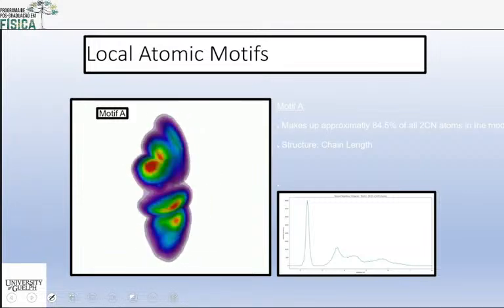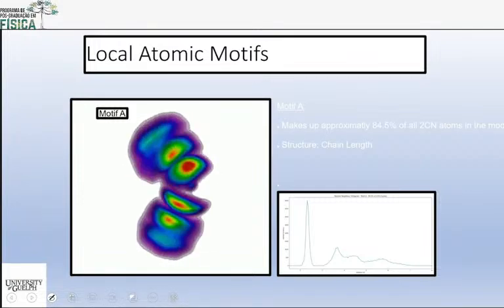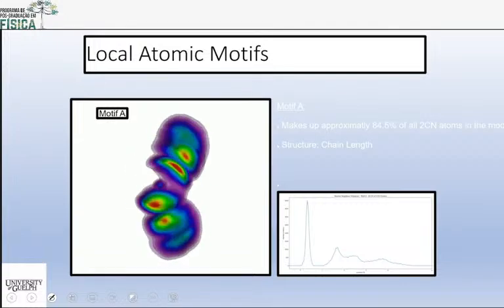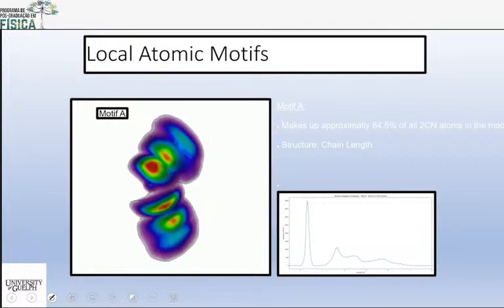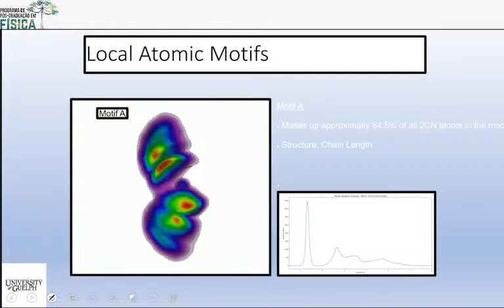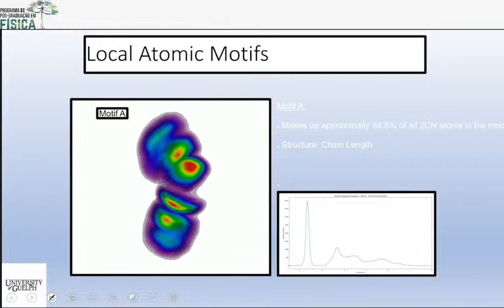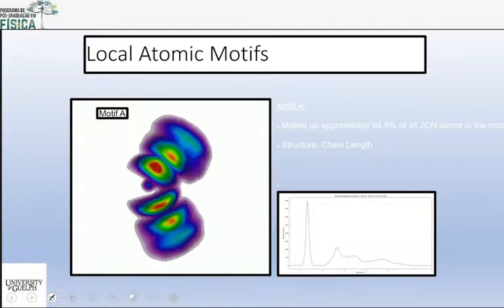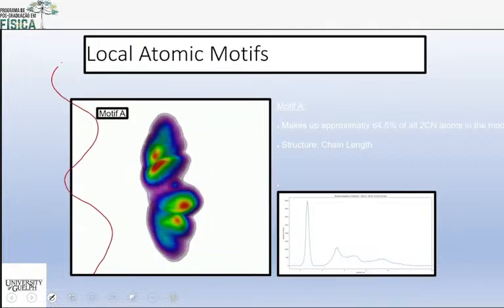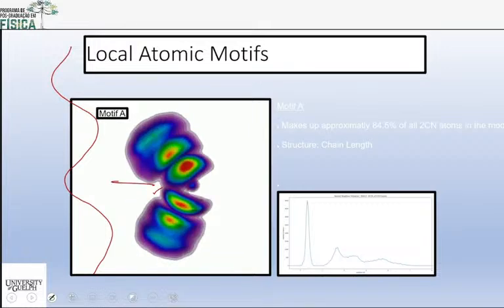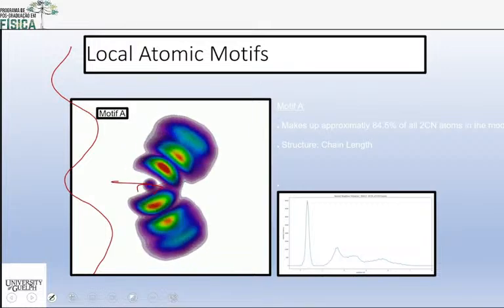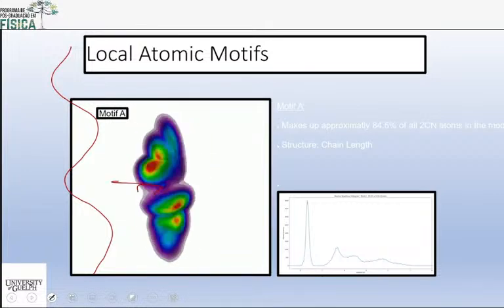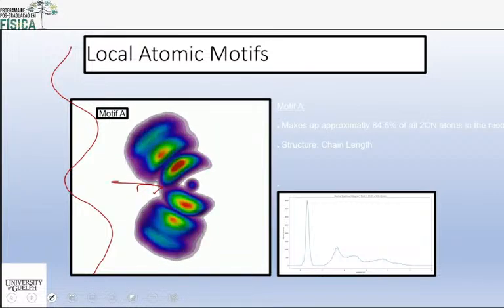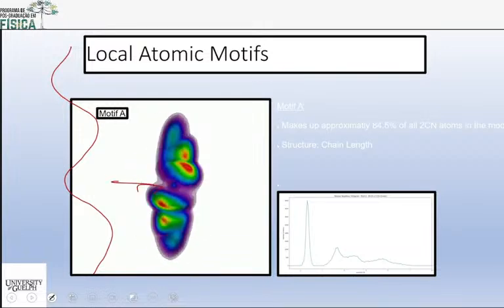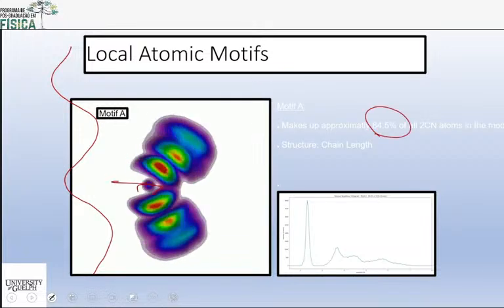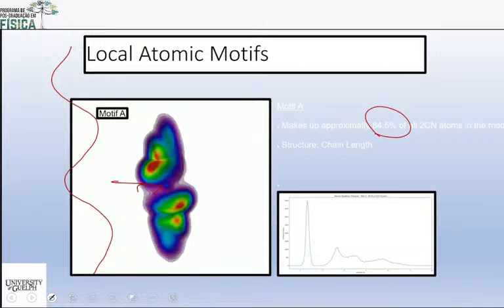And actually, this is a picture of what we see as the neighborhood around a selenium atom. So people wanted to know whether there were rings, 8-atom rings. And what we're seeing is something that maybe looks more like a chain. So you have a center atom here, and you can see its neighbors have a range of angles, and the next, and so on. But we also found that 85% of the sample in the model came out to have this local arrangement.